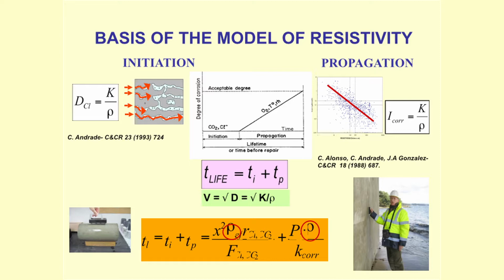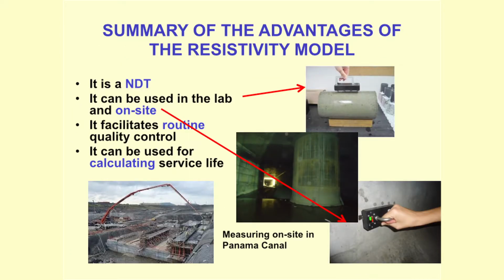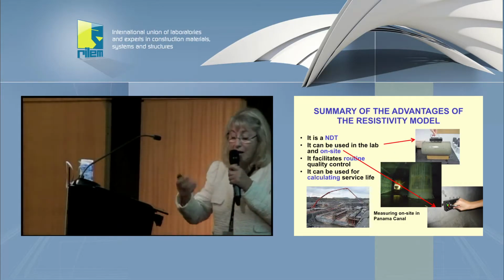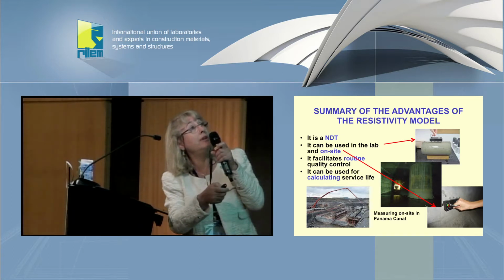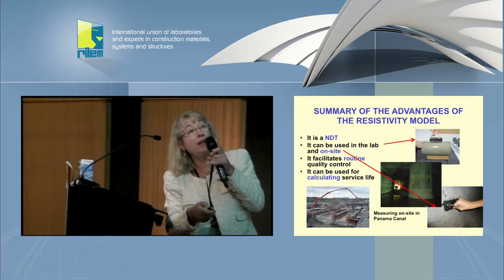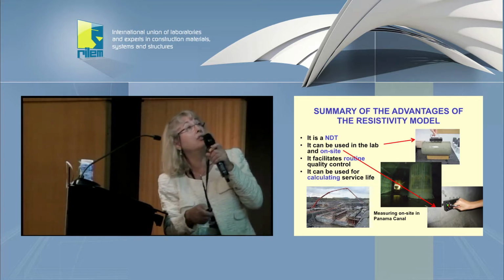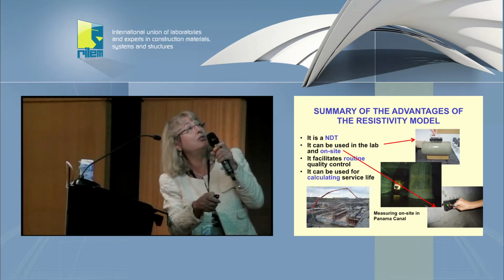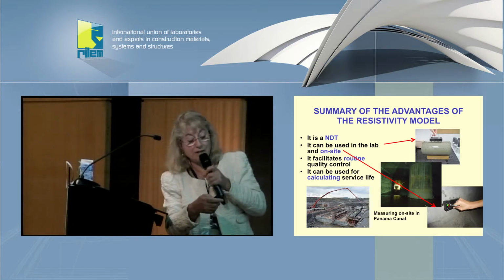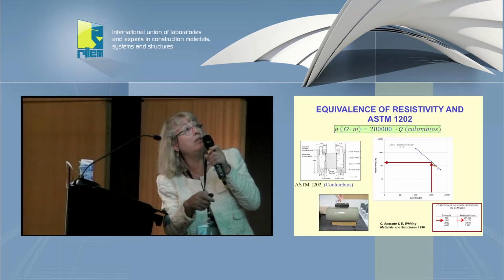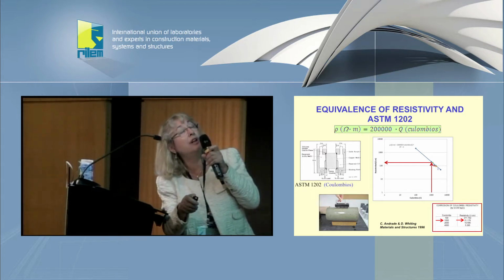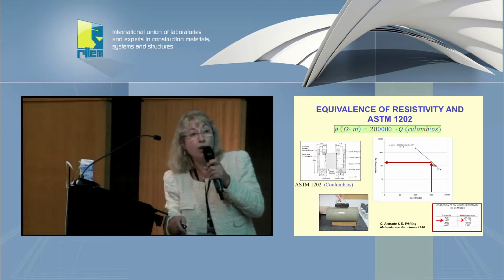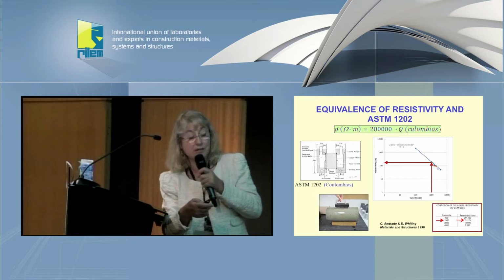In that case, it's possible using a square root law to have a service life model based on the resistivity measured at 28 days, and for aging it's possible to leave the concrete in contact with the salt water and obtain the aging factor correctly. It's a non-destructive method. It can be used in the lab and on-site. We have used it to verify the resistivity in the Panama Canal. It facilitates routine quality control and can be used for calculating service life. And it also has a correlation with the ASTM test, the coulombs: about 200 ohm meter is equivalent to 1,000 coulombs. We published this equivalence with David Whiting in 96.